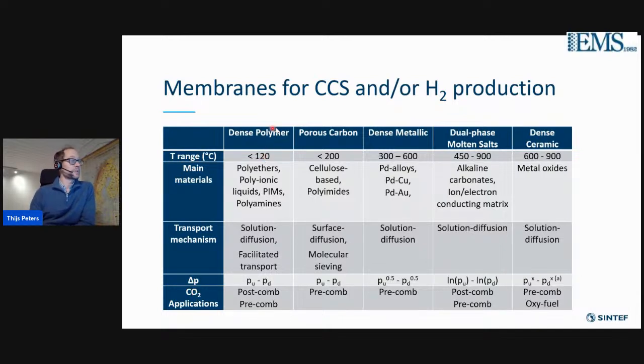So I will focus the data presentation on the dense polymer membranes, the dense metallic membranes, and the dense ceramic. The polymeric membranes are typically operated below 120 degrees, relevant for CO2 nitrogen and CO2 hydrogen or hydrogen CO2 separations. The dense metallic is typically operated between 300 and 600 degrees, where the materials are palladium and its alloys, for example, palladium copper and palladium gold. And the dense ceramics are typically metal oxides, where either the oxygen or the proton are conducted through a solution diffusion mechanism.